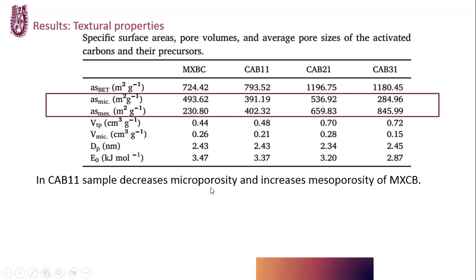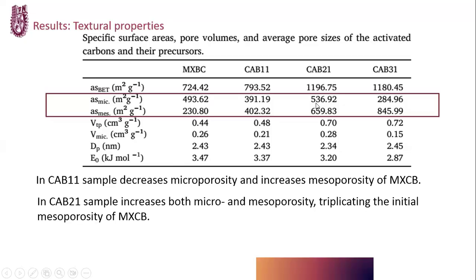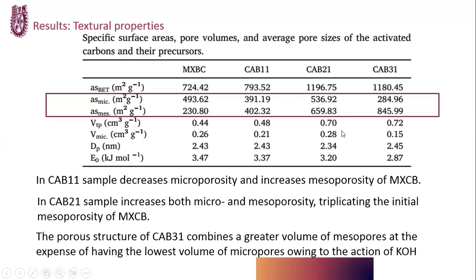Now let's talk about porosity. In activated carbon 11, we can see that microporosity decreases and mesoporosity increases relative to the original bituminous carbon. In the case of activated carbon 21, both micro and mesoporosity increase, tripling the initial mesoporosity of bituminous carbon. And for the third sample, the structure combines a greater volume of mesopores at the expense of having the lowest volume of micropores, owing to the action of potassium hydroxide.